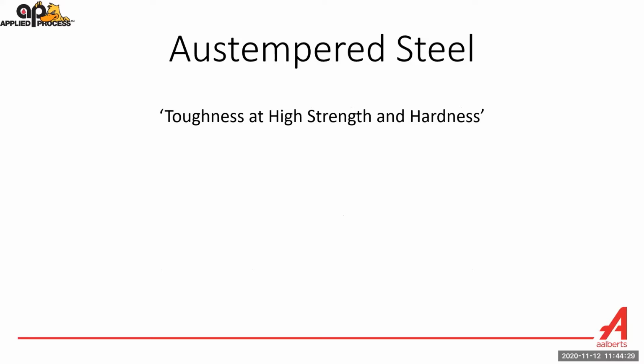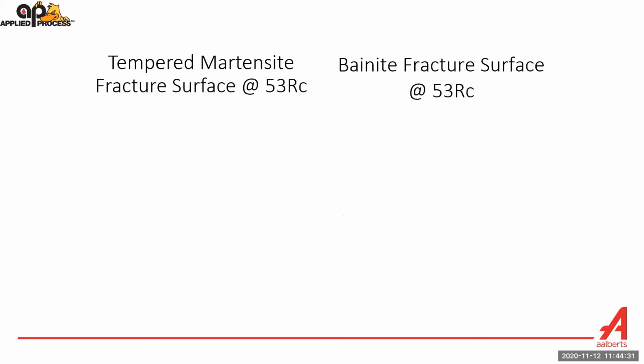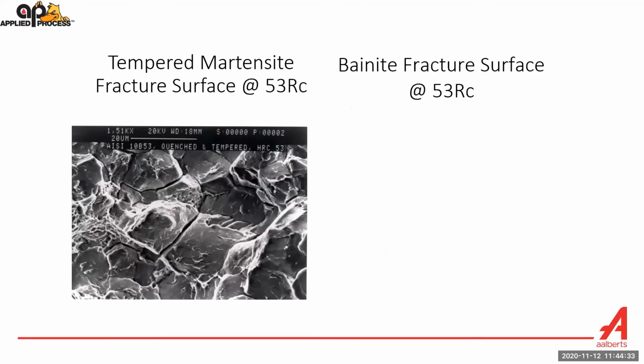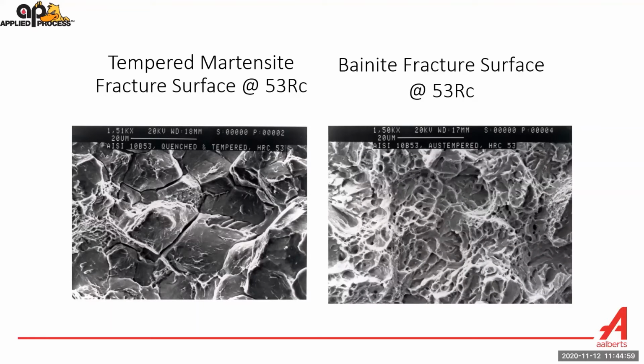Tagline is toughness at high strength and hardness. And first thing we do is we go to a microstructure. This is a fracture surface of a tempered martensite, so something that would have been oil or water quenched and tempered at 53 Rockwell C. This is what's called a brittle fracture. If we look at the same steel, I believe this was 1074 steel. Oh no, it was 10B53 that was austempered to 53 Rockwell C.